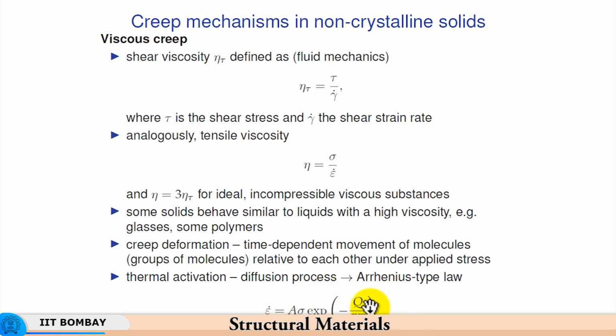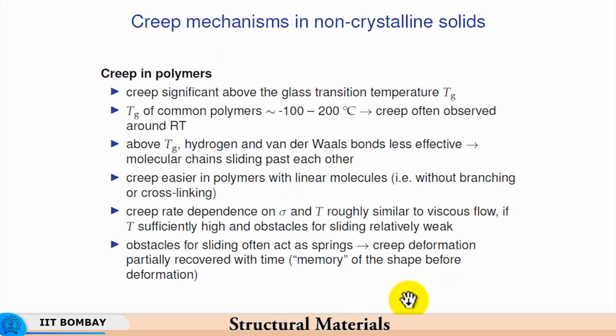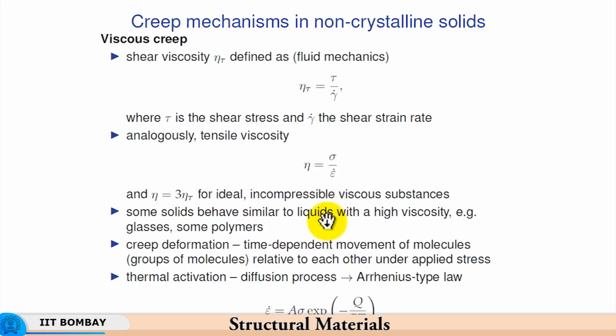So, this is the Q, which refers to the activation energy for that particular mechanism. So, Q takes the value of the operating mechanism. It is not a general value. The value of Q at any given temperature and stress condition would be determined by the operating mechanism. So, if diffusion, for example, is the rate controlling mechanism or the major mechanism, you will have Q of diffusion. That is why we have different creep mechanisms and the corresponding equations and corresponding strain rates for different mechanisms.